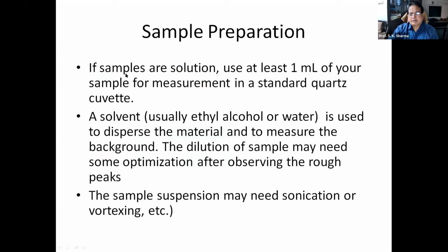So now we prepare the sample. If the sample is a solution, use at least 1 ml of your sample for measurement in a standard quartz cuvette. Solvent is usually ethyl alcohol or water, and it is used to disperse the material and to measure the background, meaning the noise, or you can say a reference kind of thing. And the dilution of the sample may need to be optimized after observing the rough peaks. Sometimes if you take a very concentrated solution, then your peaks may overshoot the y-axis. So you need to dilute the solution so that you can see the peaks.